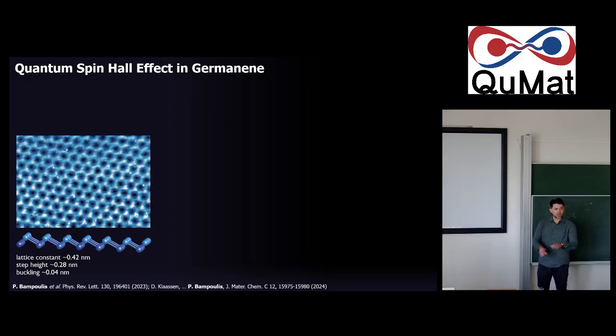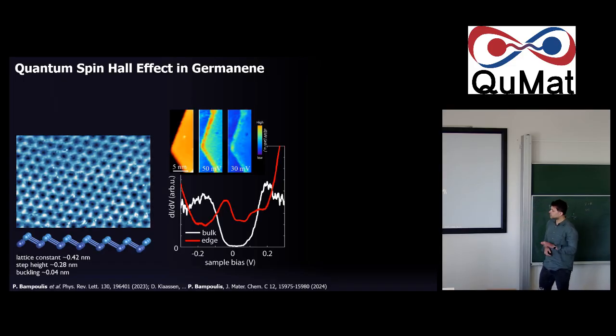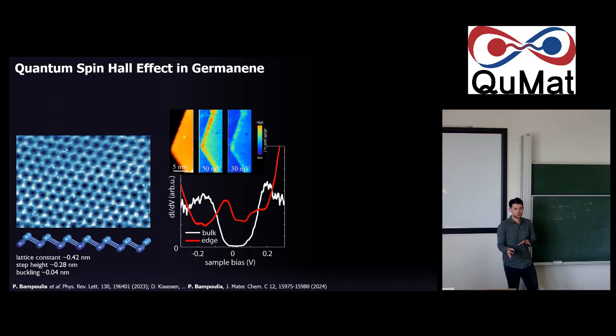You can measure step heights because this grows in layers with different thicknesses. And we also could extract a buckling, which changes a bit with the bias set point, but it is in the order of 0.03 to 0.04 nanometers. So it's about half of what you would expect for suspended or freestanding germanene. That can be explained because you have interactions from the substrate. Now we look at whether it has the properties you would expect in such a system.